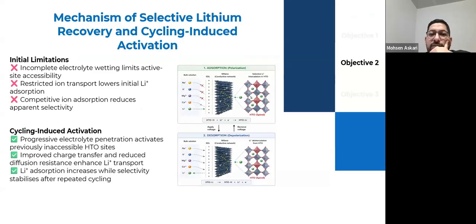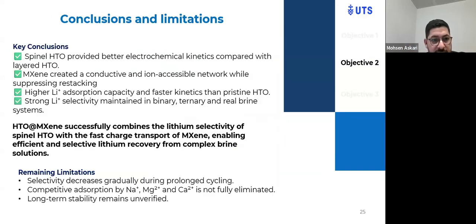As a mechanistic insight into the selective lithium recovery, we can say in the initial stage, incomplete electrolyte wetting limited active site accessibility, and restricted ion transport lowered initial lithium adsorption, and competitive ion adsorption reduced apparent selectivity. Maybe because of that, the selectivity after the first cycle decreased, but in the next cycles, the progressive electrolyte penetration activates the previously inaccessible HTO sites, improves charge transfer, reduces diffusion resistance, and enhances the lithium transport, and lithium adsorption increases while selectivity is stabilized after repeated cycling in 7-8 cycles.